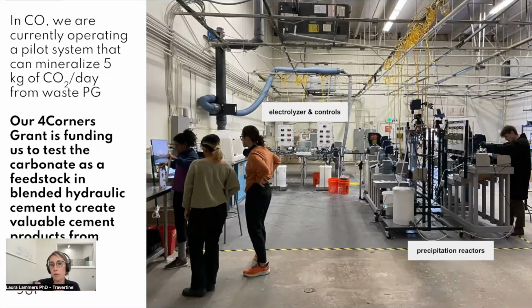And so we're going to be taking our materials, characterizing the properties, creating blended cements, testing them to make sure that they follow the ASTM certifications for strength and durability. Another thing that we can add on to this is basically testing our precipitated calcium carbonates as alternatives to the ground natural calcium carbonate in the calcination step that actually produces the Portland cement, which could make an overall net carbon negative cement material. So if you head to the next slide.